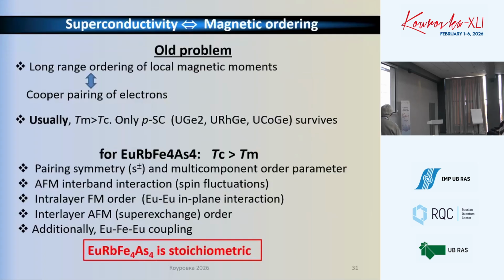And of course, the problem is rather old. As I said in the beginning, 80 years ago it was considered that superconductivity and magnetism are enemies and cannot coexist. Then a lot of materials were discovered where the magnetic ordering temperature is higher than the superconducting temperature. It means that magnetic ordering is stronger than superconducting pairing. In this case, only p-type symmetry survives, and this is observed in uranium germanium, uranium rhodium germanium, and uranium cobalt germanium. So we have a heavy fermion superconductor.